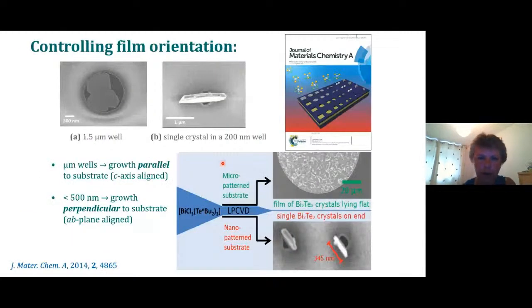We've been able to take that further and show that we can control the orientation of the crystallites within these recesses. So again, this is an SEM image of a little 1.5 micron diameter well that's been created. The dark grey is just showing some titanium nitride. This region outside is the silica, and we can see the bismuth telluride crystals growing beautifully within the titanium nitride region. And you can see that the platelets are lying flat down on the surface with the C-axis of the structure normal to the substrate.